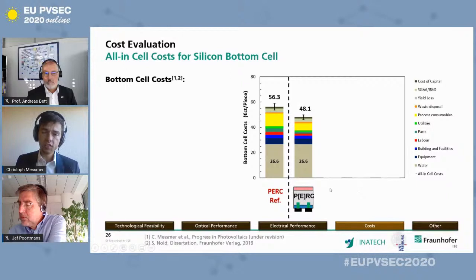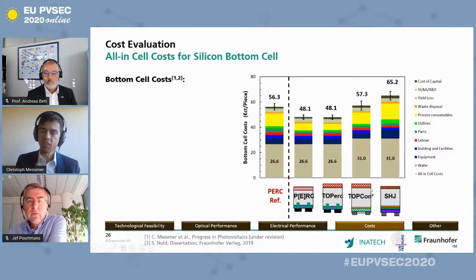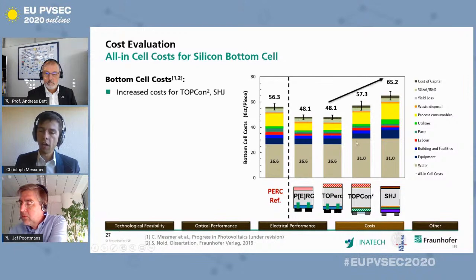And if we compare this to the bottom cell of the PERC-like structure, we see, first of all, that's less in cost, but this is mainly since we have no metal grid at the front side. However, if we compare these to the other bottom cells, we see that the TOPerc bottom cell yields a similar cost than the PERC bottom cell. However, the TOPCon squared and the silicon heterojunction concept yield higher costs.